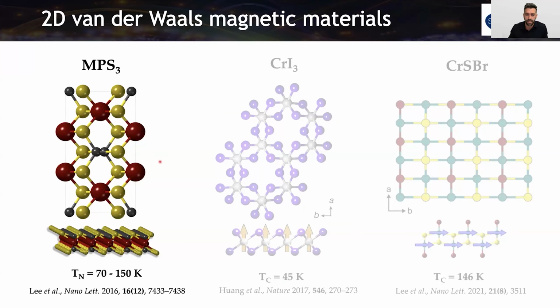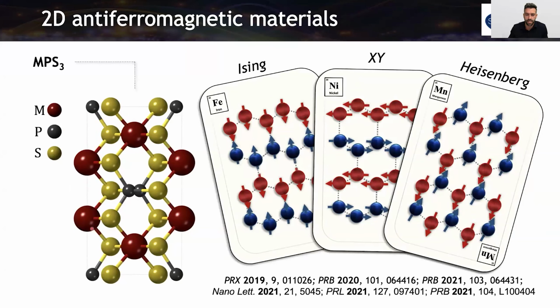Then we have also been working with transition metal phosphorus trichalcogenides. As I said before, this was in 2016 the first isolated 2D antiferromagnetic material. The interesting thing about this family, well, it has a honeycomb lattice, but also depending on the transition metal, we can have different magnetic orders, different distribution of the spins. In this case, for example, for iron, we have these zigzag chains that are antiferromagnetic. In the case of nickel, they are zigzag chains, but in this case, the spins are in plane. Here is out of plane. And for example, for manganese, we have Néel distribution. And all these works point towards the measurement and prediction of magnons in this material.